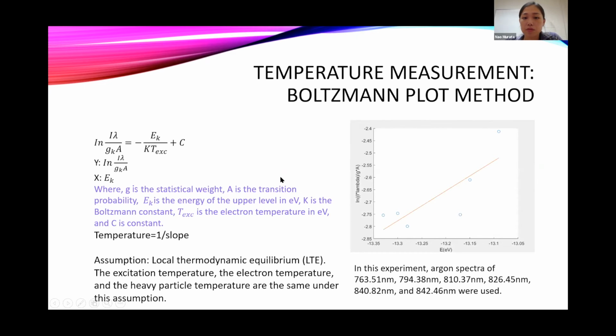And the second method we use to get the temperature of the electron is the Boltzmann plot method. This is the main equation for the Boltzmann plot method. We make the scatter plot with MATLAB, and the y-axis is going to be the natural log of intensity times wavelength over G times A, where G is the statistical weight and A is the transition probability. And the x-axis is the energy of the upper level in eV. So we plug in the intensity and wavelength values from the OES data. And in this project, we use these 6 different wavelengths.